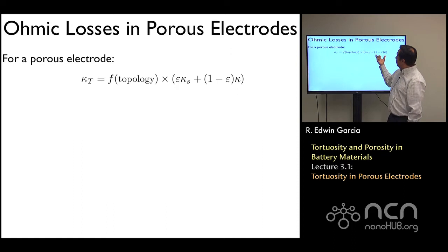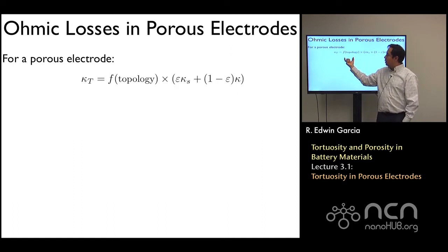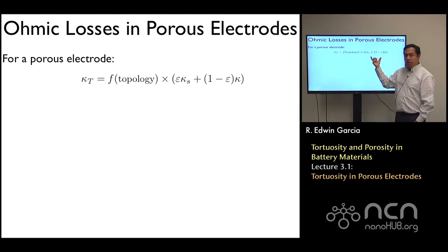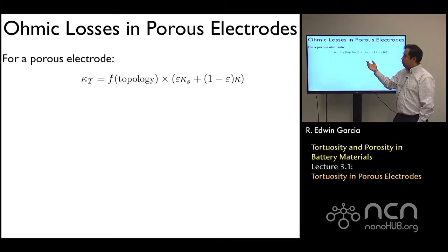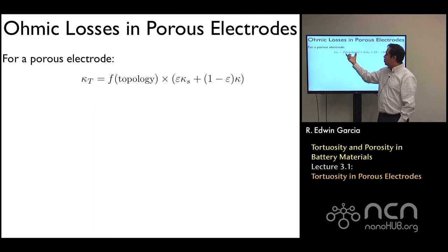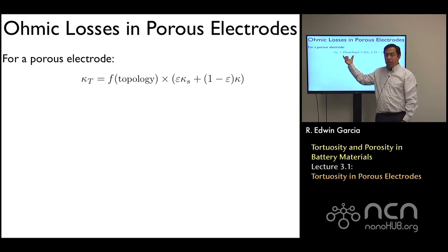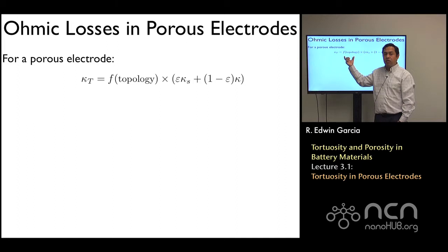In practice, however, there is a geometrical contribution that modifies that. Even though we can insist on specifying this rule-of-mixture type description for the conductivity of the system, we have to determine what that relationship for the conductivity is. What people have figured out is that this coefficient or function — associated to the topology of the conductivity — can really be related in terms of a quantity that people refer to as tortuosity.